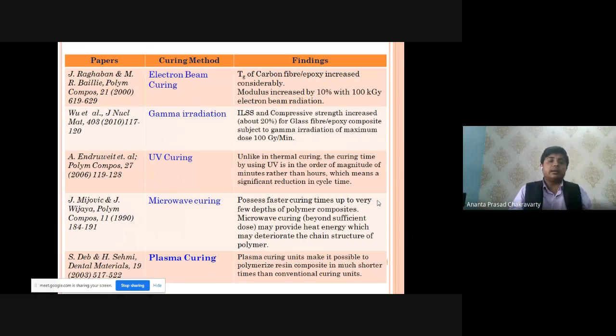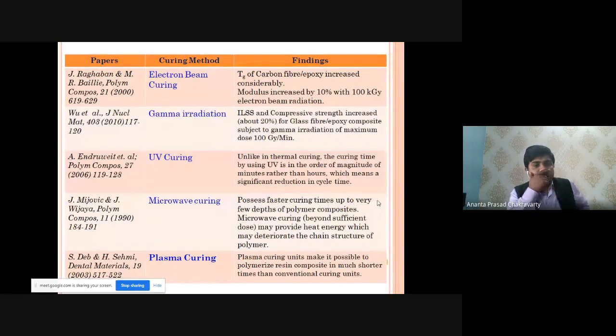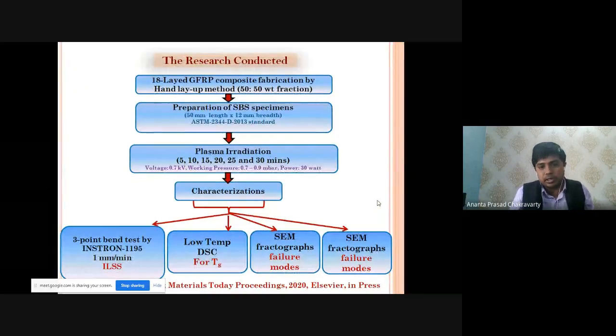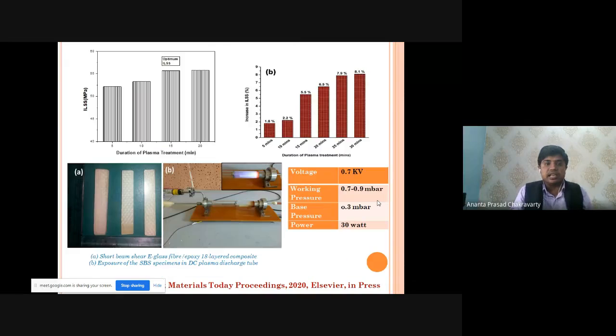So with respect to different curing methods like electron beam curing, gamma irradiation, ultraviolet curing, microwave curing, and plasma curing, from different researchers, I went for plasma curing. This experiment was conducted at C.V. Raman Global University. I exposed these materials up to 30 minutes of plasma irradiation, and I can see that its interlaminar shear strength improved considerably within a very limited interval of time, around a 20% increase in 30 minutes of plasma exposure.